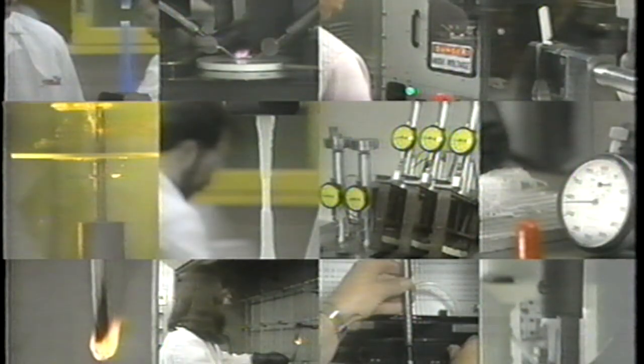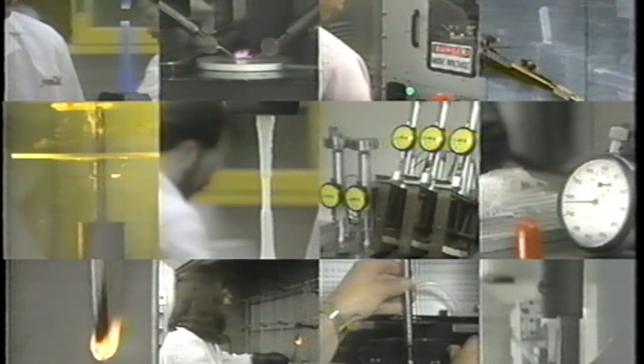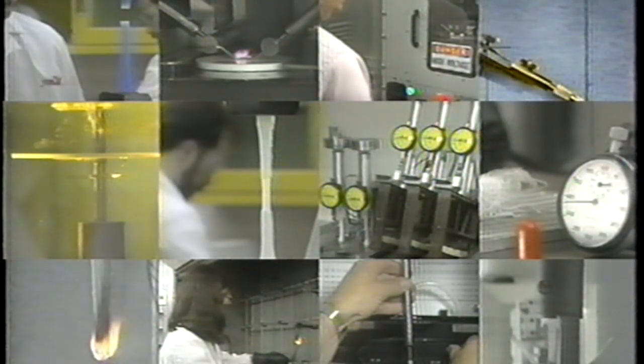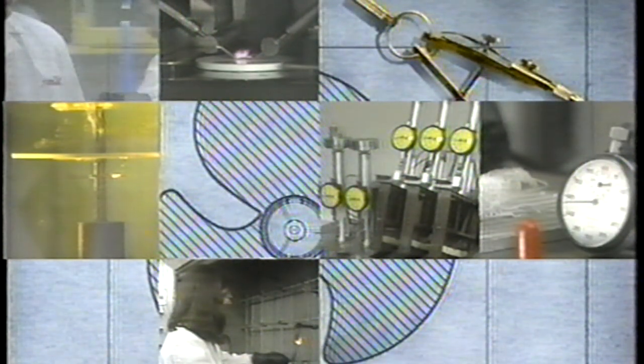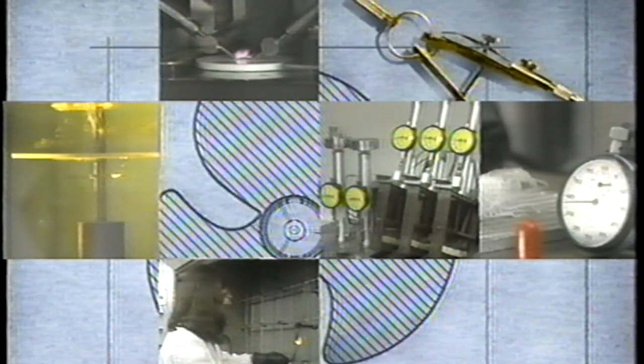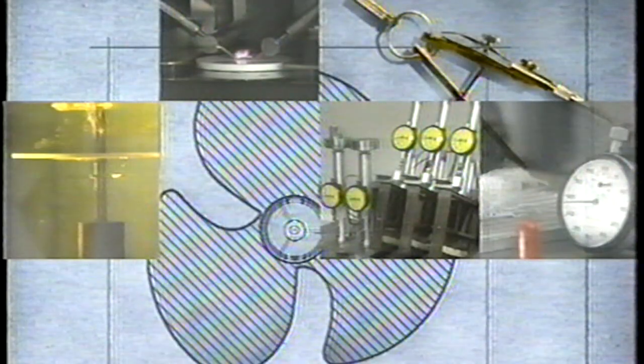So when looking at possible materials, we can automatically rule out any product with an IZOD impact resistance below 4 foot-pounds per inch of notch. The list of possibilities is now more manageable. From here, we might look at the thermal or electrical properties and eliminate any materials that are close to limits or out of range. And the list gets shorter still. Next, we might examine the mechanical properties a little more closely. We can tolerate some elongation at load, but not much, or else the part will deform. So out go the materials with high elongation values.